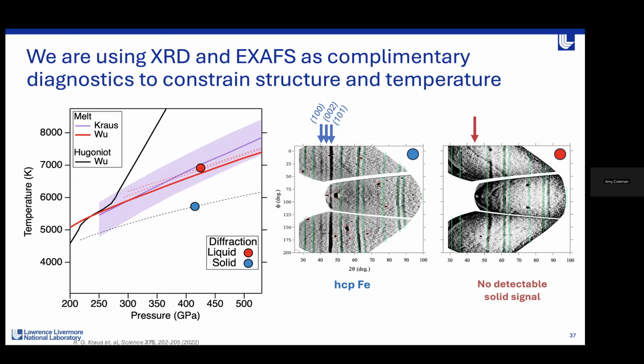The reason for that is we're using very thin iron layers in these experiments, something on the order of 6 microns, and this is unfortunately below the threshold in this image plate diffraction setup where we'd be able to see liquid signal. So typically in these experiments, we take the loss of any solid diffraction peaks as us entering the liquid regime.